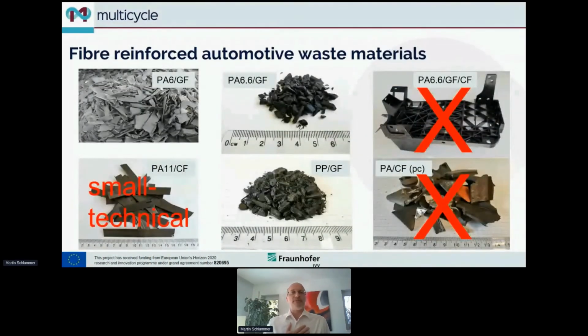Let's go back to the fiber reinforced materials we got from the consortium. Here you see that we finally focused on the PA6, PA66 glass fiber material, and the PP glass fiber material. Why? The PA11 carbon fiber was not supplied in sufficient amount. The PA66 carbon fiber glass fiber is not much more challenging than this one. However, in our filters, we cannot distinguish between carbon fibers and glass fibers, so whatever we do here doesn't bring any added value. So we decided not to use that one as an in-feed for the large scale demonstration.